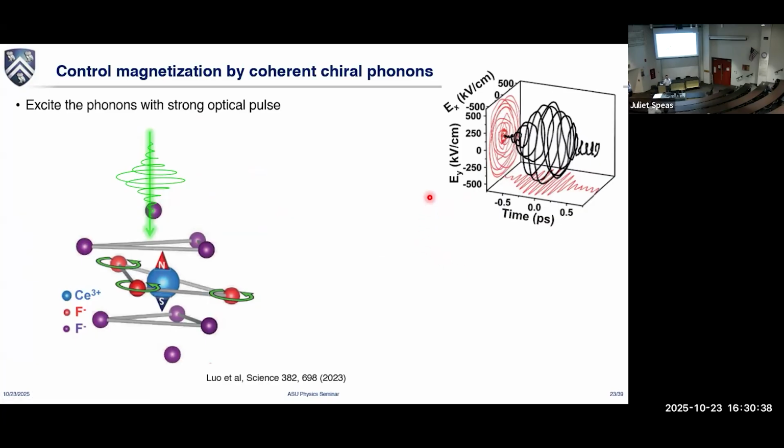You put two near infrared pulses together, and the difference frequency is set to, in this case, 10 terahertz. Through nonlinear crystals, it will create a pulse. Then the next thing is actually pretty simple. If we split the two pulses into orthogonal polarizations and then delay one, we create a circular polarization, right? But that has to be manually done. That's how we do it here.